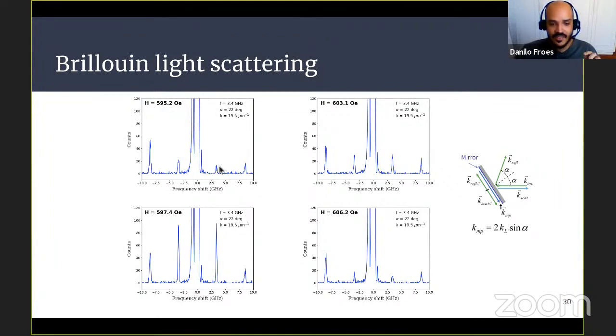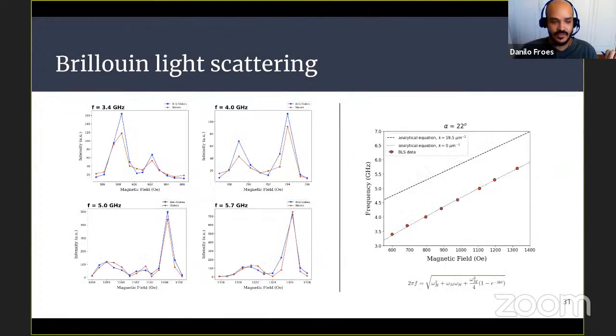But we do have another peak here, the Stokes and anti-Stokes, that corresponds to the same frequency as the radio frequency excitation. So we measure these peaks, the counts of each peak, and put them in these graphs for each frequency. Each point here is one spectrum that we obtained. And as you can see, we have a maximum in each of them. So I take this maximum magnetic field as a function of frequency and put it on the graph.